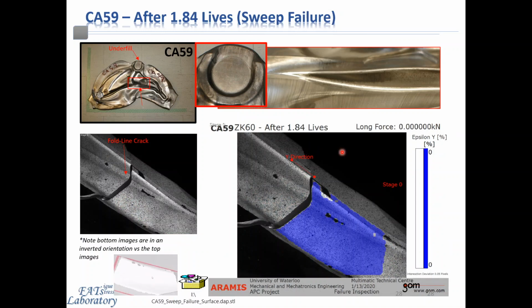Moving to the final failure, which occurred at 184% of the target life, we can observe that the final failure was due to the first crack, which was the one that initiated here, and it occurred at a different location from the first forged component, which begs the question as to the microstructural origin. Is that the cause of this disparity in crack nucleation location?